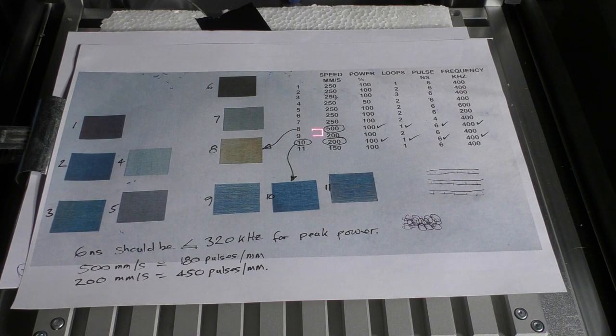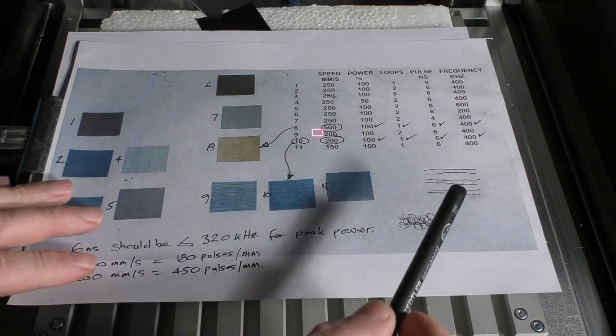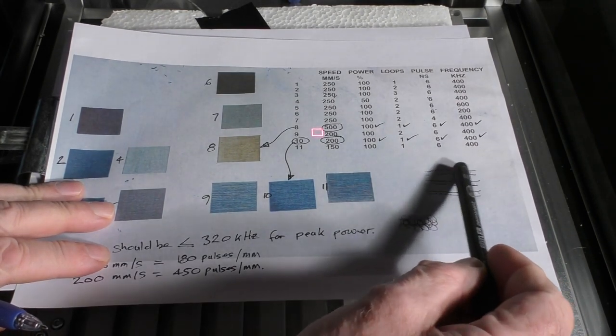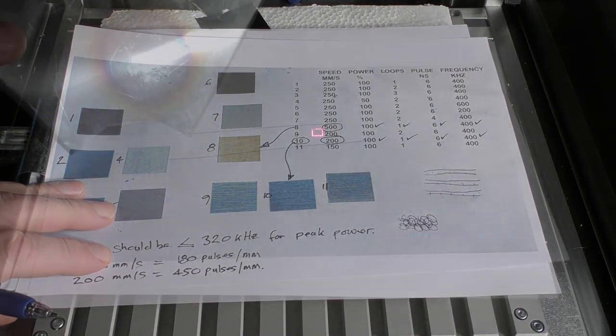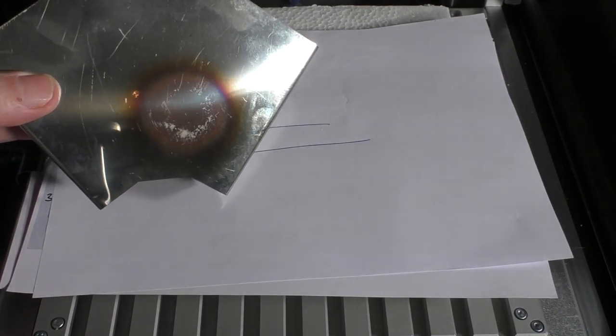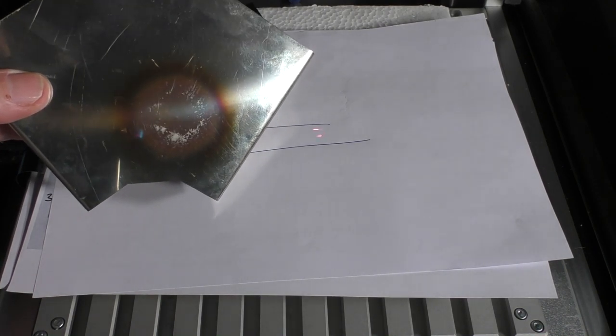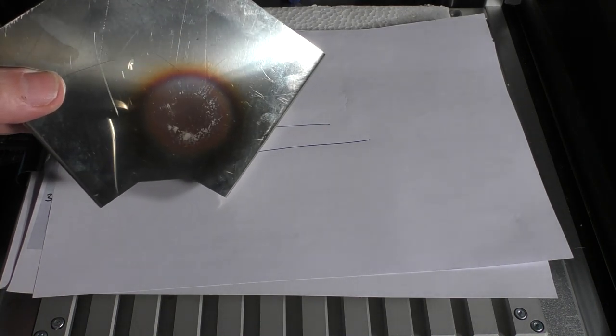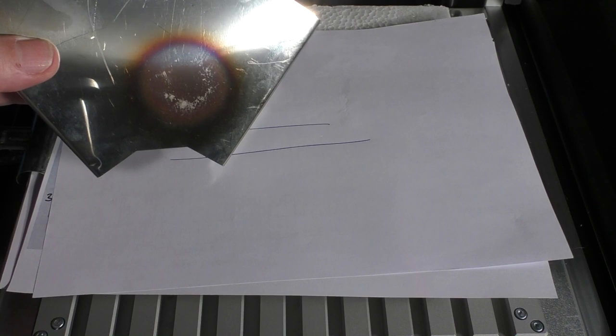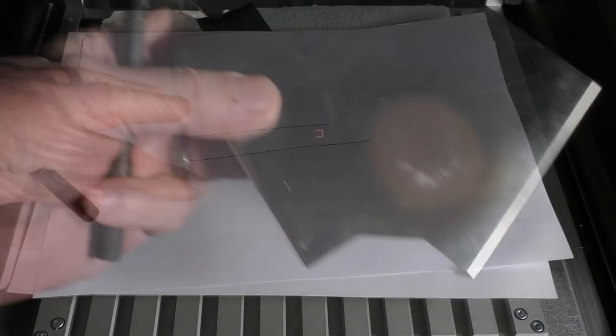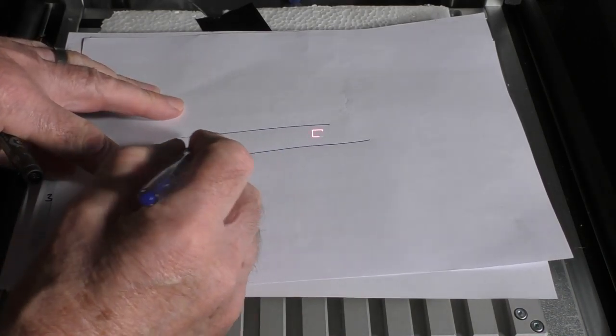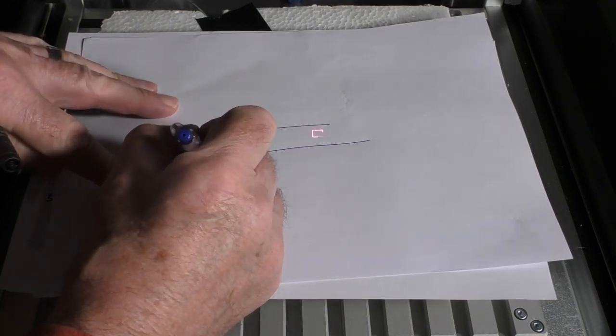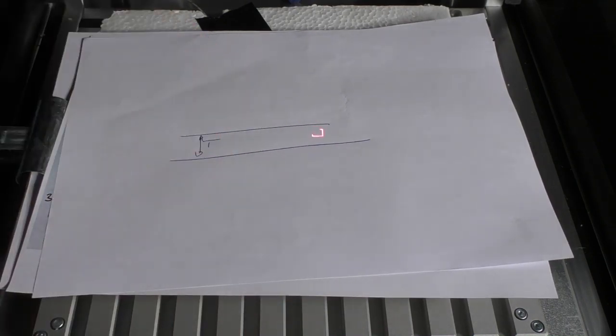I think the last time we looked at it, we found that this gold one here was actually caused by lines, and in the lines we were finding gold patterns. So what this tends to indicate is that my little pattern of interference colors, which as you can see I've managed to get them back by using not daylight but halogen work lamps as opposed to LED work lamps, have got a wider spectral range and I can see the real colors in this light. But what this does mean is that the pattern that you've just seen is caused by a variation in the thickness of this, as we said before, T, which is the thickness of the oxide film.